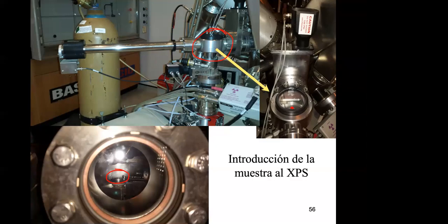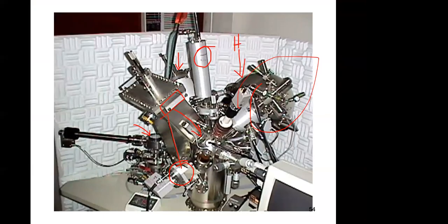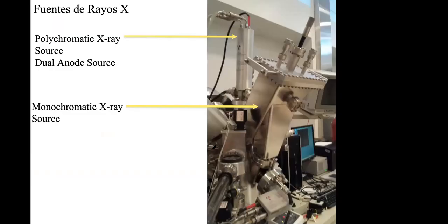One of the things that you see here is that in this chamber, all of the X-ray sources, analyzers, and ion guns are concentric. They are all looking into the same spot on your sample. That's very important: you have everything aligned to one point on your surface. That's why it's a round chamber and everything is looking inside. So again, this is the monochromator. You have the X-ray source here, the crystal is here, and then the X-rays hit your sample.